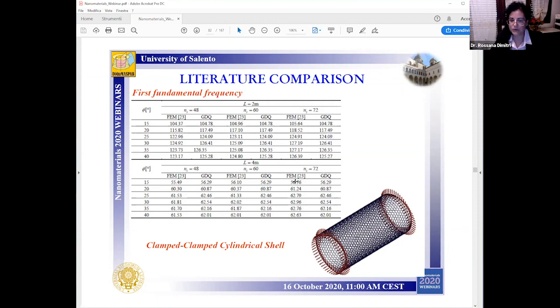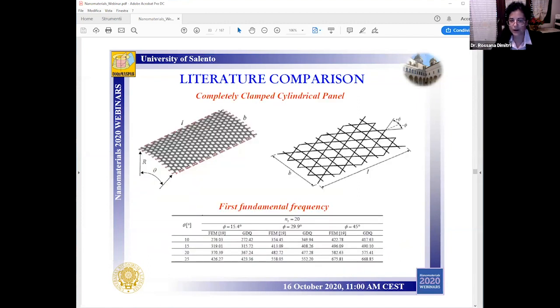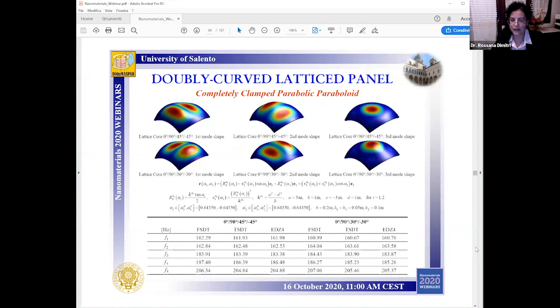So the very good agreement between our results and predictions from the literature confirms the accuracy of the proposed formulation to treat the problem. And this is also confirmed for the further example of a completely clamped cylindrical panel or a clamped three-layered doubly curved shell with an internal lattice core made of 4 different ribs families and 2 sheets at the top and the bottom side of the lattice core. And here you can see in this table the results for 2 different sequences of the ribs family of the core with a very good matching between our numerical results according to differential theories.